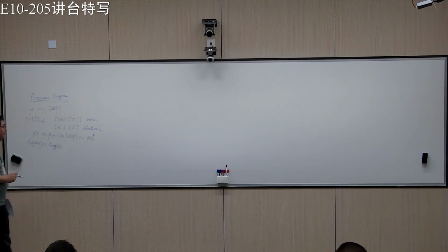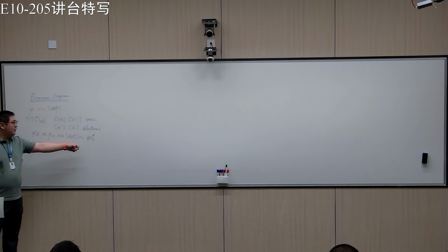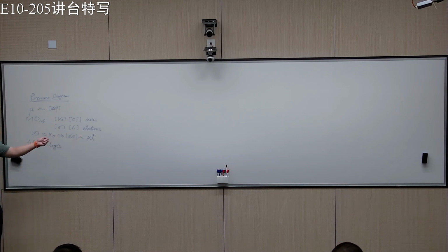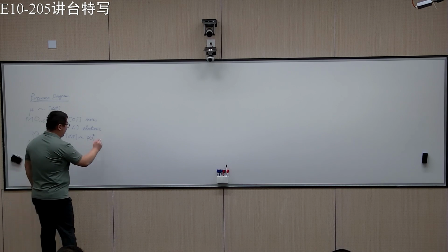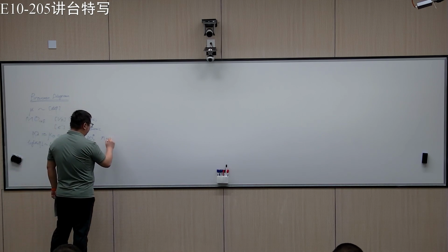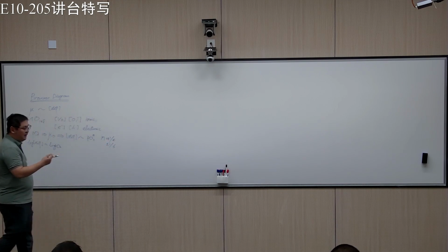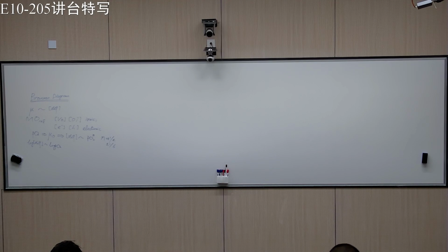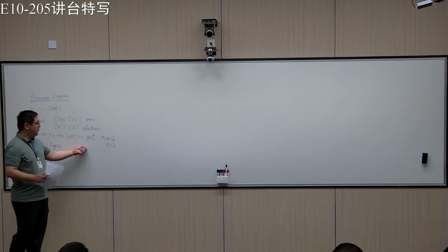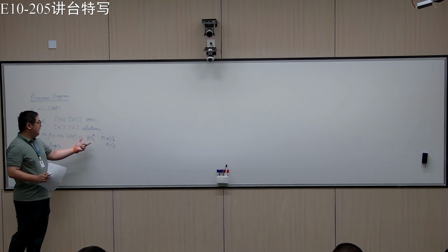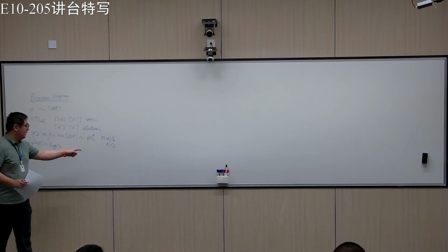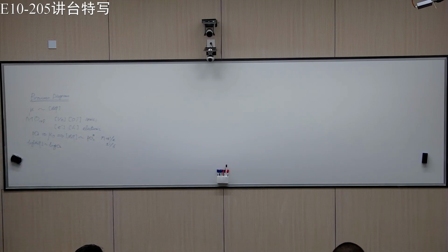So you have a power law of PO2 and this n is the power. We find that n will be something like plus or minus 1/4, 1/6, depending on which regime you are at. Of course, the natural solution is to take the log on both sides, then n becomes the slope in this plot.